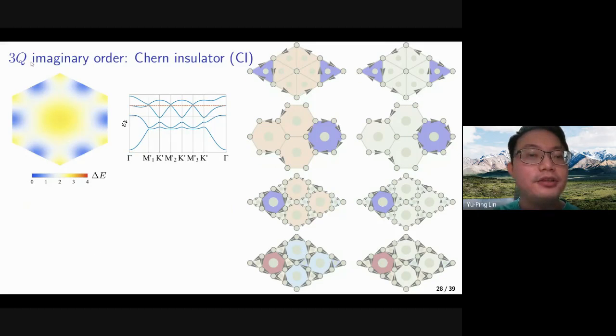The next thing to look at is the 3Q imaginary order. We see that at the Fermi level, the band structure is fully gapped. And as we have said previously, it is a Chern insulator. And you can see that on the lattices, there are some current orders. Because it breaks the time reversal symmetry, the quadratic band crossing here is gapped.